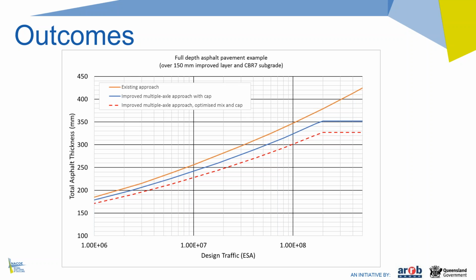The difference between the top and the middle lines is the reduction in asphalt thickness that will be able to be realised immediately, and that's even without the mix-specific design approach that Eric's described. Optimising the mixes for fatigue performance will lead to a further reduction in thickness, somewhere below that middle line. And the bottom dashed line there is to illustrate just where that line could be with the right mix. We can also see from this chart that the traffic limit of 200 million ESAs that Jeffrey discussed, if you look at the middle line there, is on the basis of using this new traffic method.